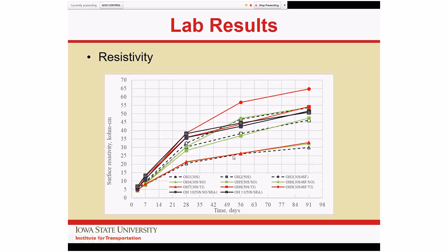So the chart, again, lots and lots of data, but what it's showing us is that the three systems of 30% slag have an acceptable, but still relatively low resistivity. High is good, low is less good. Now, typically, other states are saying you want to be around or above 28. And so we got pretty close to that with all of these mixtures.